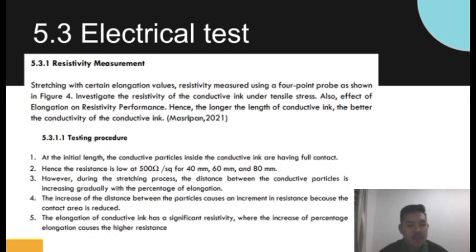Okay, the procedure: at the initial length, the conductive particles inside the conductive ink are having full contact. Hence, the resistance is low at 500 ohm per square for 40 mm, 60 mm, and 80 mm. However, during the stretching process, the distance between the conductive particles increases gradually with the percentage of elongation. The increase of distance between the particles causes an increment in resistance because the contact area is reduced. Elongation of conductive ink has significant effect on resistivity, where an increase of percentage elongation causes higher resistance.